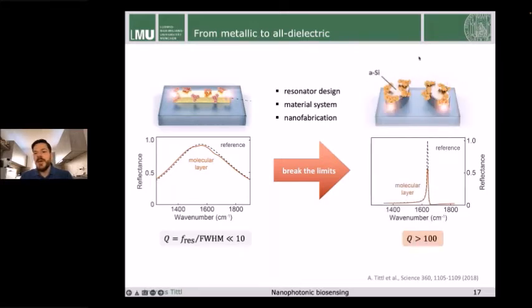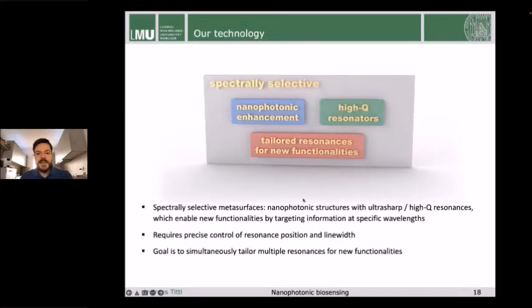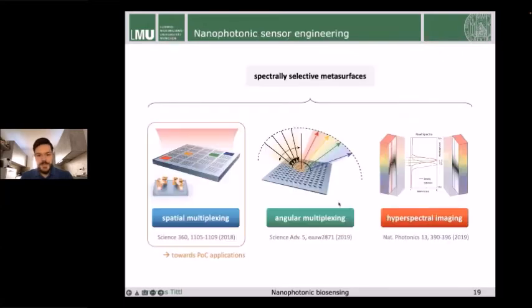And what we ended up with is such elliptical resonators made of amorphous silicon, which is a lossless dielectric in the mid-infrared. And we found that we were able to make resonances that are extremely sharp and can be used to precisely target a given molecular vibration and to read it out with much higher sensitivity than was previously possible. And this is actually the main research topic in my group. We call this spectrally selective metasurfaces, because they really allow us to pinpoint specific biological information with great accuracy.